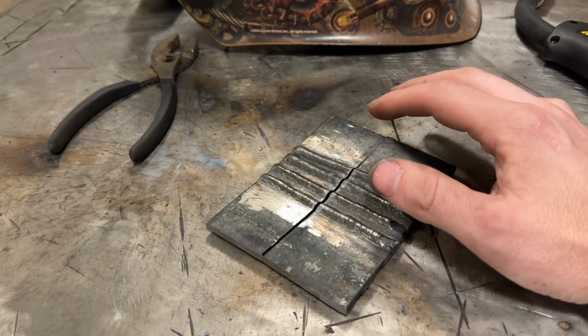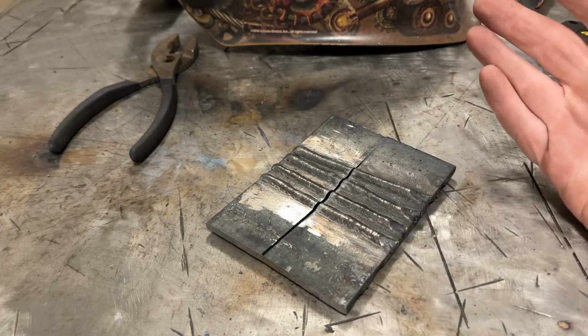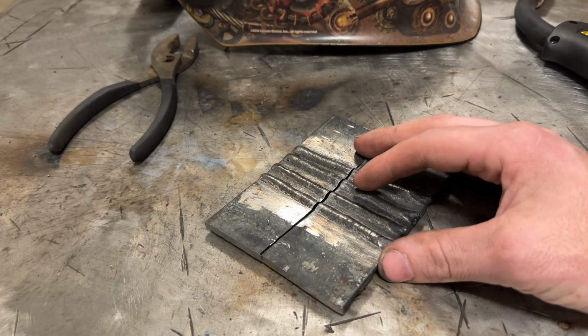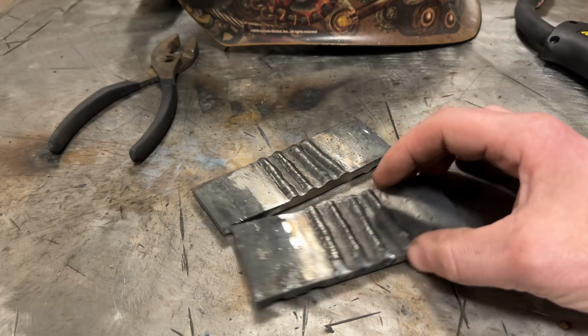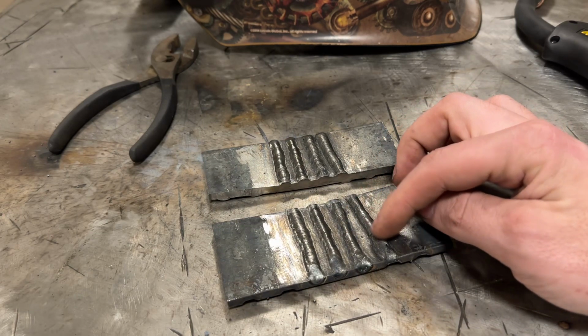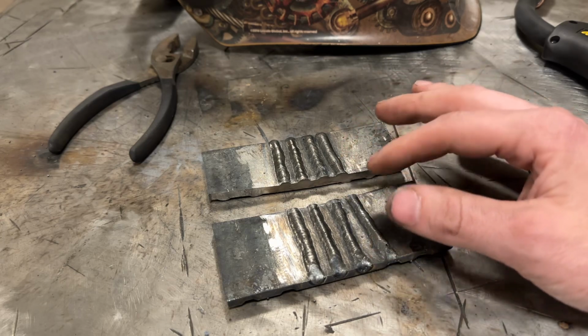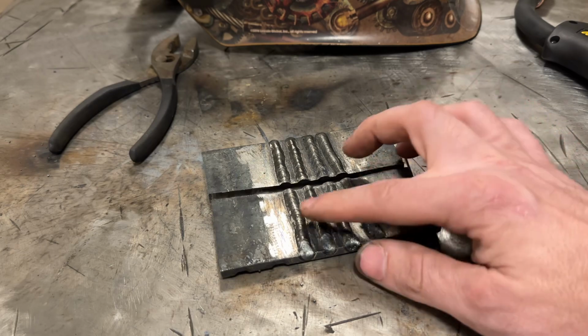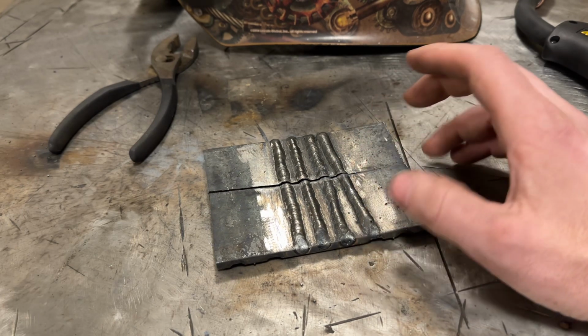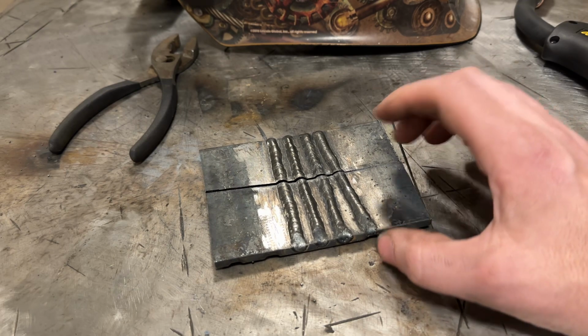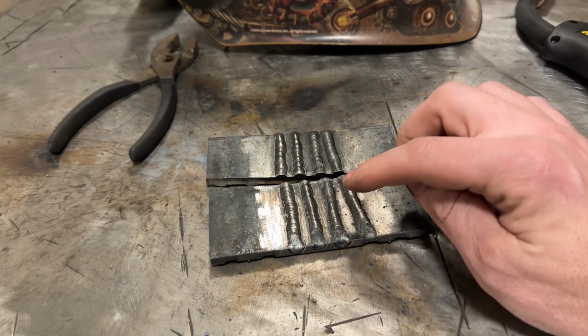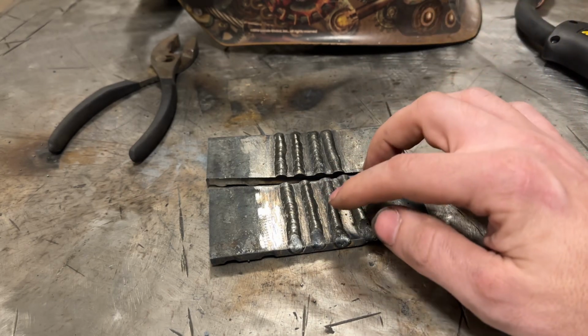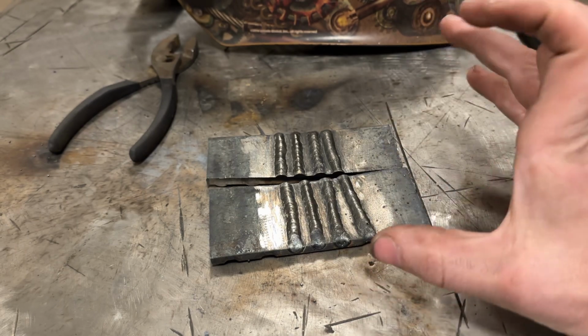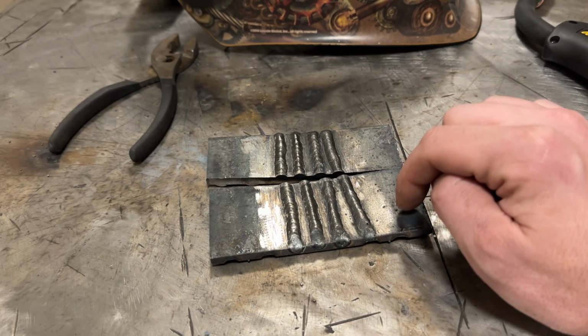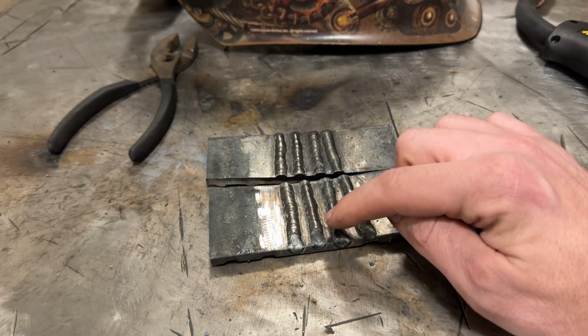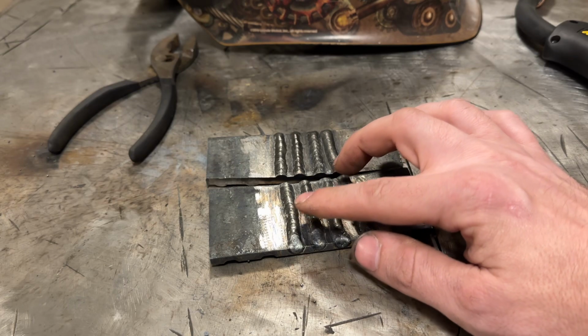So those results were a little bit different than what I had expected, to be honest with you, but then again, I didn't come into this video with high expectations anyways. But the gas shielded welds had better appearance overall, no evidence anywhere on them of porosity, and you saw in the cut and etch that these two that were self-shielded did have porosity. Now, like I had said up close, I think a lot of that porosity is simply because that molten metal solidified so fast, because the settings weren't hot enough for this plate, that the gas didn't have enough time to escape that molten pool, therefore it was trapped inside.